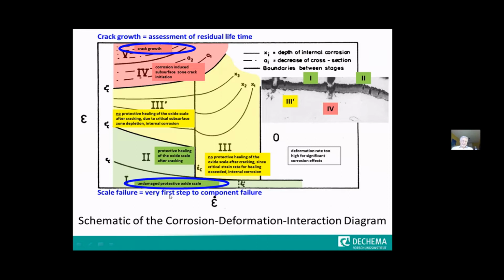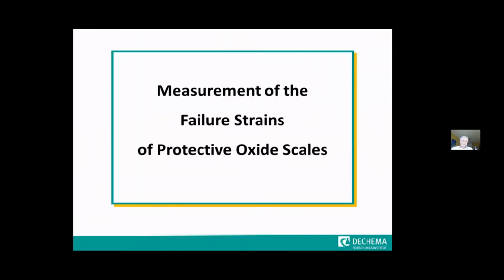Because that is the very first step leading to component failure after a while, after going through all these stages up to the one where the corrosion-assisted crack growth may take place. And that is the last stage. So that's the other point which I would like to address today quite briefly, which means the very beginning and the very end of life under the effect of combined stresses and corrosion at high temperatures.